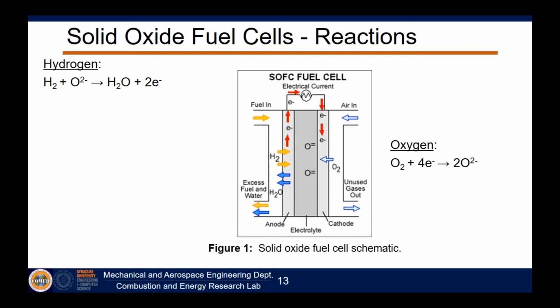The only challenge with carbon monoxide, though, is that occasionally at certain temperatures, this what's called inverse Boudouard reaction actually becomes very favorable. And if that's the case, we can actually deposit carbon within the anode, and after a period of time, that anode can be completely covered in carbon, and it's no longer able to transport the fuel through it. So the fuel cell will no longer work. Carbon we have to deal with, but it's possible if we can control the temperature properly.